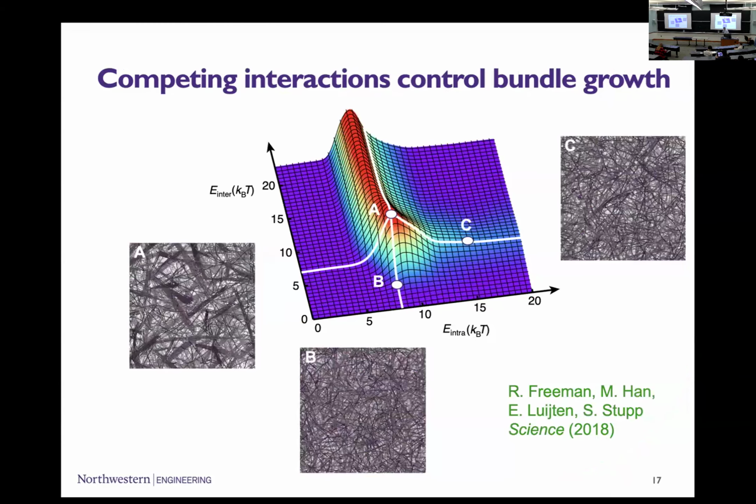But what is really interesting is what you can do in a simulation, where simulation takes off and can do things that experimentally are very hard. We say, look, there are basically two things going on. There is a strength of binding of the DNA. If that strength is not strong enough, you don't form a gel at all, obvious, right? The crosslinks are simply, if they're like half a kT, the system doesn't care. But on top of that, you also have to think about how strongly is the DNA bound. And maybe I should explicitly say that because that might not be obvious.